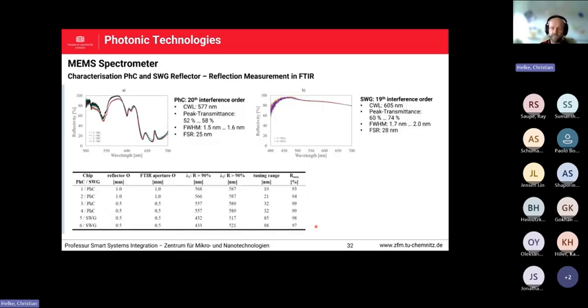And now I'm coming to the final slide. So the characterization regarding the reflectance measurement, for example. On the left-hand side, the nanostructured silicon nitride membrane. On the right-hand side, the metal patches on the silicon nitride layer itself. Again, we wanted to have a reflectance in the range of 570 to 600 nanometer, in the range of 93%, which is comparable to the PhC reflectors.